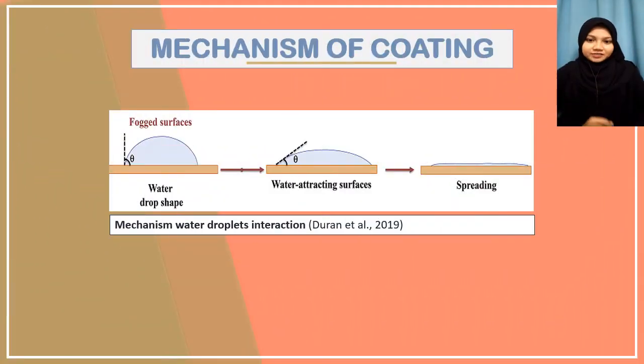This figure explains the mechanism of the coating. First, the water is dropped on the glass slide and it has a water drop shape. After that, it has a water-attracting surface with the thin film. After some time, the water droplet spreads into a continuous thin film on the glass substrate, and this effect is known as hydrophilicity.